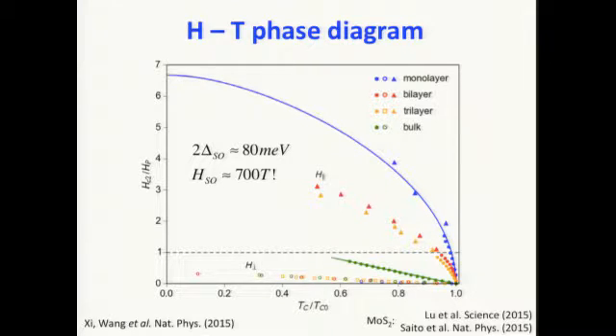And actually, we can do a simple fit to the data and try to extract the energy scale relevant to the system. It's confusing here that the argument actually works in the monolayer, but once you move on to bilayer or trilayers, you basically break down this symmetry, right? So there's no more Ising spin-type locking expected in the bilayer or trilayer, isn't it? Yes, actually, very good question. I'll go to the next slide. I'll answer your question on the next slide.